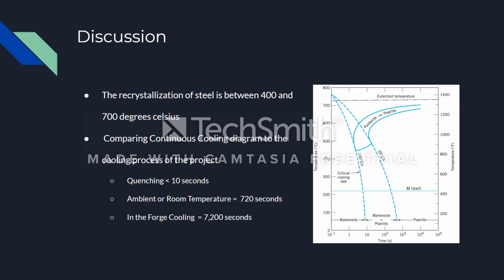The martensite microstructure has very hard properties. Secondly, we did the ambient or room temperature cooling process, and it took 720 seconds to cool. You can see on the continuous cooling diagram, 720 seconds should be right in this area. So the second subject is a martensite and pearlite microstructure, mostly pearlite and just a little bit of martensite. So it should be a relatively hard material as well, just not as hard as the 100% martensite.